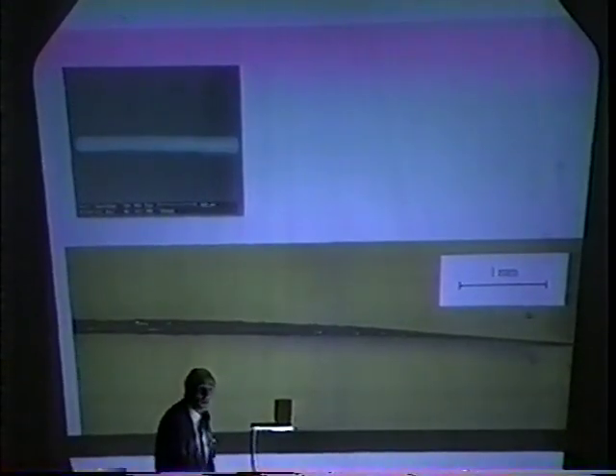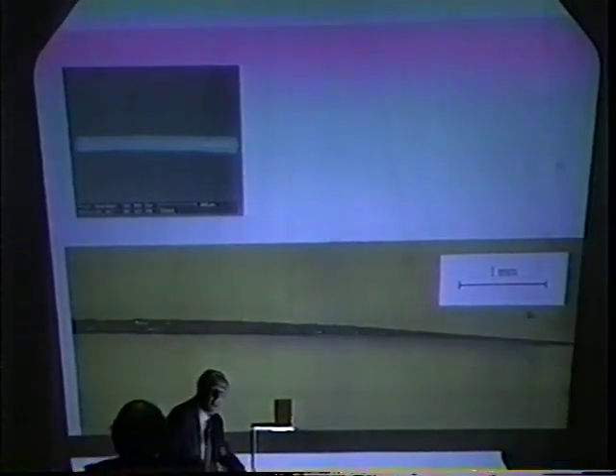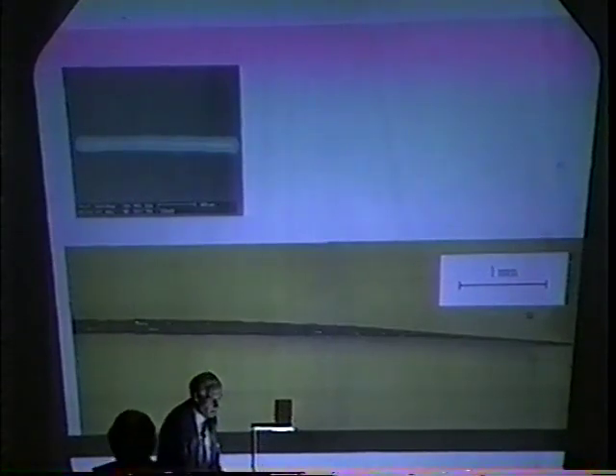This is a cross-section view of the material. The clear line in the middle is the tungsten substrate, and around it is the titanium deposited. You can see the scale here: the thickness of the layer is about 200 microns, the width is about 4 millimeters, and the total length is about 4 centimeters.